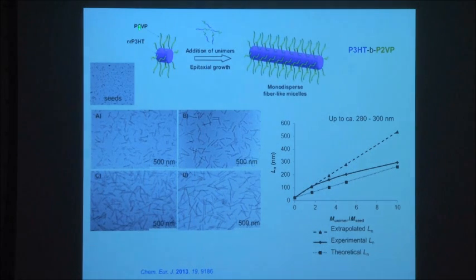Here's another system. This is poly-3-hexylthiophene-poly-2-vinylpyridine. Again, you can make seeds and then you can grow these structures. In this case, you can grow them a bit longer, up to about 300 nanometers, but you have the same problem where we believe you're introducing defects. So as you try and grow longer and longer, you find their real length decreases relative to the length you expect. So we've been trying to solve this problem. We've recently had success in that. We can slow down the self-assembly and make much better cores, and we can get longer structures up to about 700 to 800 nanometers.